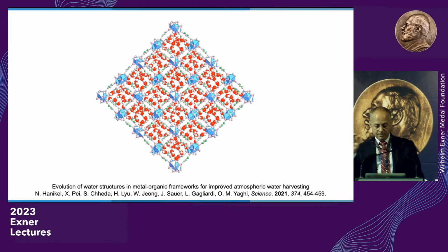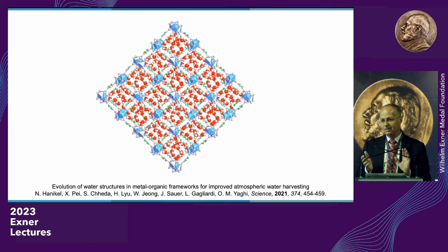So it turns out that we are able to locate each water molecule incrementally as we fill the pores using single crystal X-ray diffraction. MOF 303 is heaven sent, actually. It's perfect. It has the perfect binding sites. It takes up 45% of its weight in water. It works for many, many years.